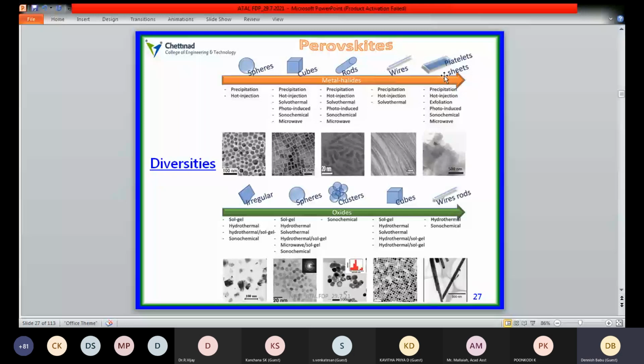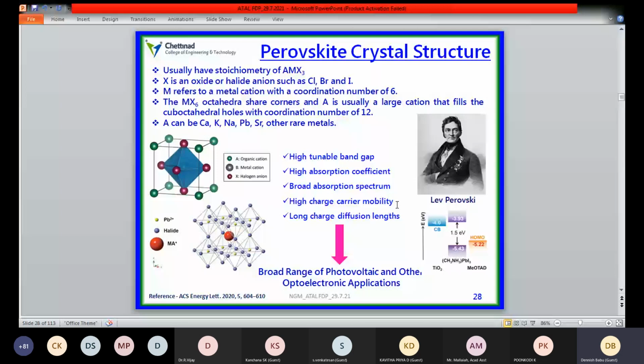As I mentioned earlier, the perovskite crystal structure has the stoichiometric ratio of AMX3, with the A-site cation, the M B-site cation, and X being a halide atom. And these perovskite materials have excellent properties like a highly tunable band gap, high absorption coefficient, broad absorption spectrum, high charge carrier mobility, and long charge diffusion lengths. These are the five major properties of this perovskite material for use in multiple optoelectronic device applications.